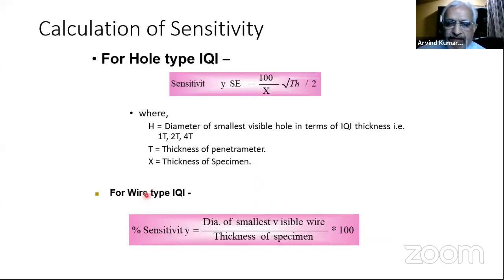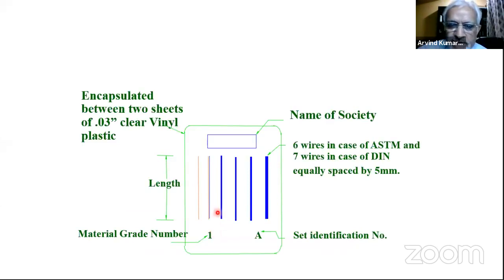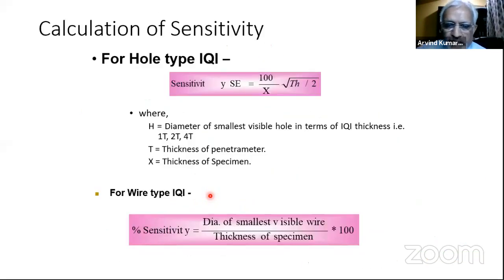How to check that sensitivity for wire type is a very simple formula. Diameter of the smallest wire that I am able to see in the radiograph. Suppose out of this, I am able to see this wire. So this is the smallest wire I can see. I'm not able to see this. So that smallest wire, and what is the thickness of my job? So suppose I am able to see a 0.2 mm wire on a 10 mm thick job, into 100. So I have 10. So 2% sensitivity I will get.